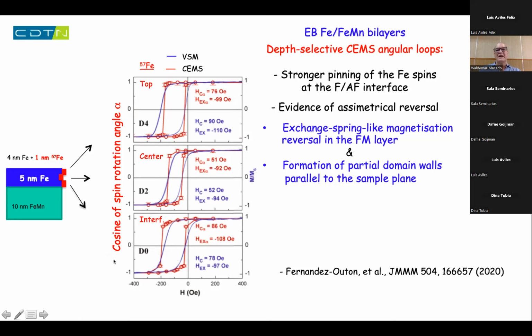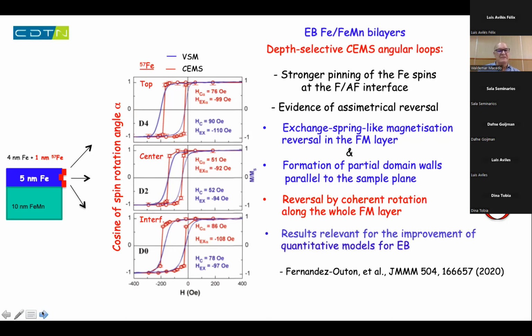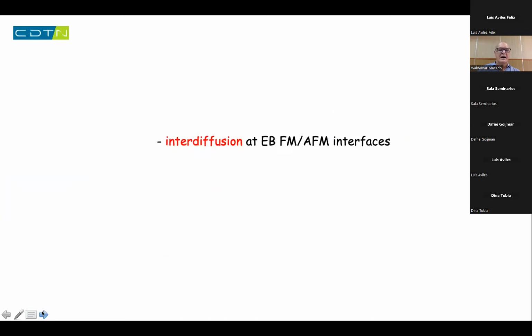That means you see a clear sign of an asymmetrical reversal. We have one kind of reversal when going from positive to negative: an exchange spring-like magnetization reversal. And when you go from negative to positive, you have a reversal by coherent rotation of the whole ferromagnetic layer. This is important for the theories of exchange bias.